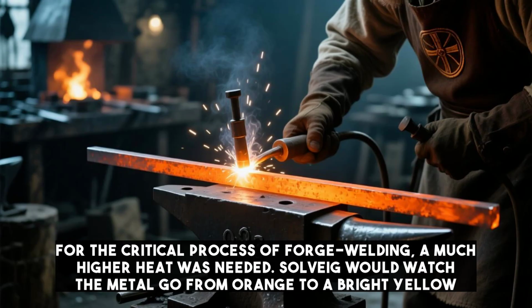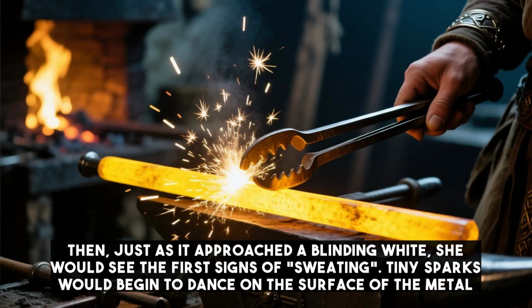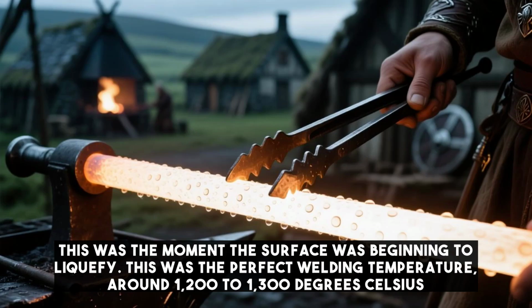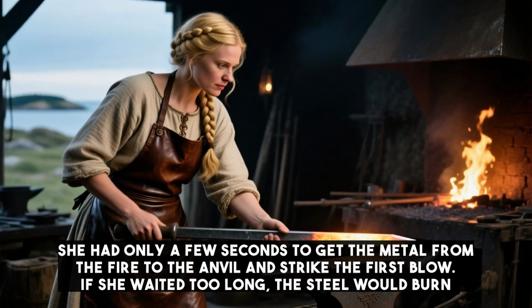For the critical process of forge welding, a much higher heat was needed. Solveig would watch the metal go from orange to a bright yellow. Then, just as it approached a blinding white, she would see the first signs of sweating. Tiny sparks would begin to dance on the surface of the metal. This was the moment the surface was beginning to liquefy. This was the perfect welding temperature, around 1,200 to 1,300 degrees Celsius. She had only a few seconds to get the metal from the fire to the anvil and strike the first blow.